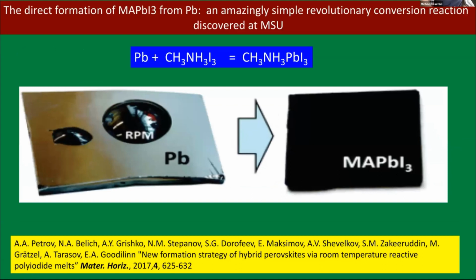But then I should give credit to our colleagues from MSU, and you see Professor Goodilin and Tarasov. They came up with a very, very elegant way. They just converted lead in one shot to the lead perovskite. You see the equation up here, lead, and how is that done? Well, with the ionic liquid, which is methylammonium triiodide. The iodide itself is a solid, but if you add iodine, you make the triiodide. And so the iodine oxidizes lead to lead 2+, and then you have everything to make the perovskite.